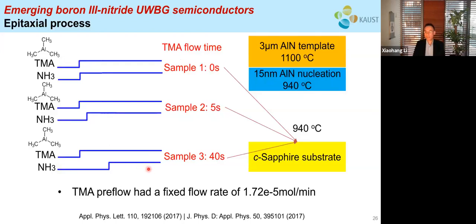So that's why we conducted three experiments. The first is to not flow any trimethyl aluminum before the growth, right? So we just grow aluminum nitride directly on sapphire. For the second sample, we flow 5 seconds of trimethyl aluminum before the growth. For the third sample, we flow 40 seconds before the growth. So different times correspond to different doses of molecules deposited on the sapphire substrate for pre-treatment.